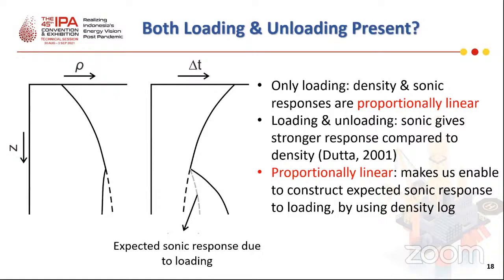Now, what if both loading and unloading are the generating mechanisms of overpressure? Dutta in 2001 stated that density and sonic log response are proportionally linear for overpressure that is generated only by loading mechanism. If sonic log response is stronger than the response of density log, then it can be deduced that unloading contributes to overpressure in a given well. This linear proportionality also makes us able to construct the expected sonic response to loading, thus loading contribution to total overpressure, by using density log.